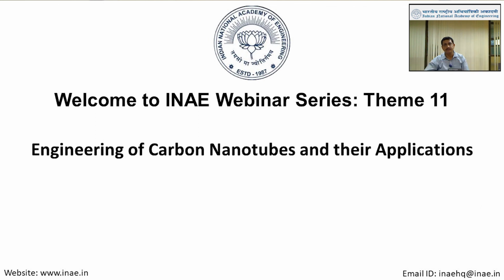There we have discussed why carbon fiber is behaving in that way and carbon nanotube in the other way. There is one note from Dr. Pradeep. How do you separate carbon black from MWCNT? Carbon black is basically a disordered structure of carbon, which has a very low oxidation temperature. Whenever you get the product, you oxidize it at 350, where carbon nanotube does not undergo oxidation but carbon black does. So this is the method we follow.